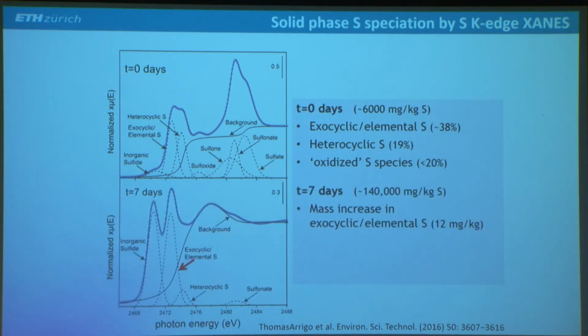After spiking and incubating for 7 days, we have a very different spectrum. And we have 2 peaks that are strongly enhanced. One is this peak for elemental sulfur, which could also be exocyclic organic sulfur, but it's very likely that elemental sulfur is here a big contributor. And then also this second peak for inorganic sulfide, which was very small here, is now very strong. And this indicates that there might have been precipitation of mackinawite as an inorganic sulfide mineral.